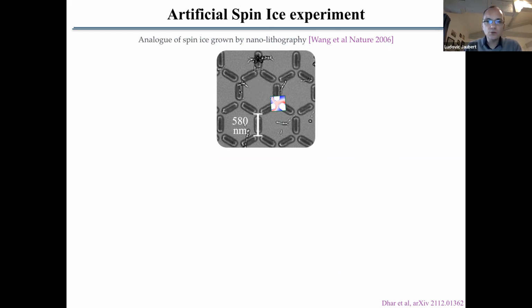By nanolithography, you deposit nanoislands of permalloy. Typically, it's permalloy. It can be something else, but typically it's permalloy. Nanoisland of permalloy here, and because they have this anisotropic shape, it's elongated, they can behave like local Ising moment, Ising degree of freedom. So locally, it's as if you have magnetic moment going this way or this way. So these nanoislands, they really behave like a local Ising degree of freedom, and if you look at them, locally, it looks like a Kagome lattice. So it is like simulating an Ising Kagome lattice in a 2D plane.